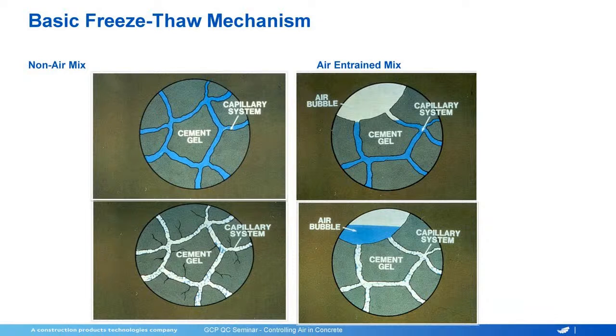So what happens in an air entrained mix? Well, these voids, they have that coating on them from the solution of the air entrainment mixing with the water and the cement. So it makes them a bit resistant to water penetration. So what happens? They are empty. All the capillaries are full. Then that water starts to freeze and expand, and it pushes itself out into these air voids. And that's how we get the protection from those cracks that you see over here, and they don't occur over here.